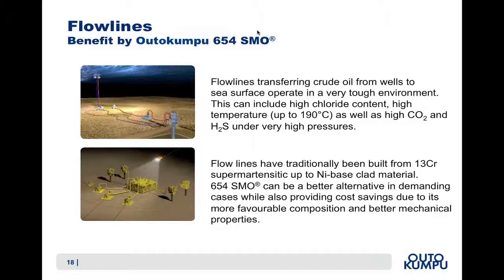This is an environment where we find high levels of corrosion due to the sea and other factors, high temperatures, as well as significant pressures. These flow lines have traditionally been made with super martensitic 13 chromium steel grades up to nickel-based cladding material. In this case, 654 SMO can be a cost-efficient alternative.